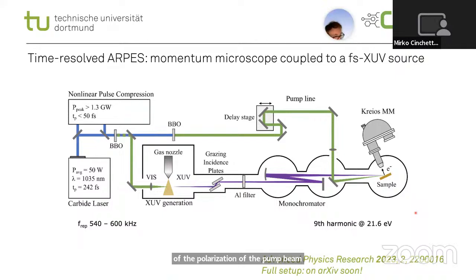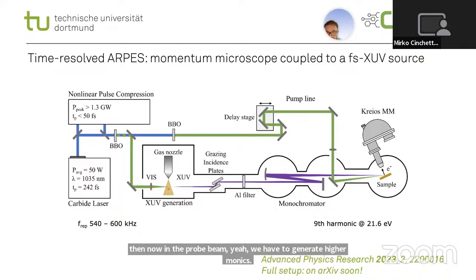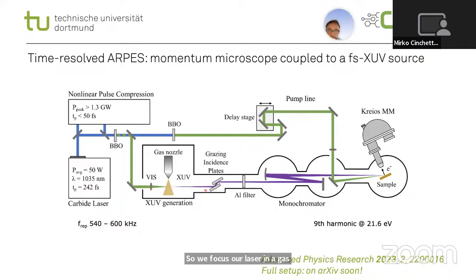The time-resolved ARPES setup is shown here. This is also a pump-probe setup, with the difference that now in the probe beam, we have to generate high harmonics. So we focus our laser in a gas jet, and this allows us to generate high harmonics of the fundamental up to 70 electron volts. And these high photon energies are needed because we use the probe photons now to photoemit the electrons. And these electrons are then analyzed using a so-called momentum microscope.